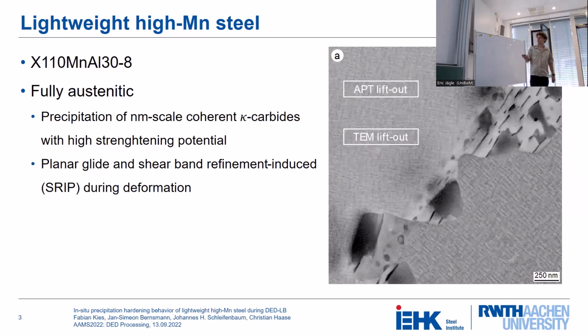In the microstructure, it kind of looks like this. This is an ECCI image. You can see this kind of basket weave microstructure in here, and these are very fine cuboid kappa-carbides with a size of about 10 to 20 nanometers. And you can also see that most of the time some kind of grain boundary phase is forming. This is also kappa-carbide, but it's incoherent kappa-carbide phase. And this leads to a couple of problems in additive manufacturing we're going to get to later.